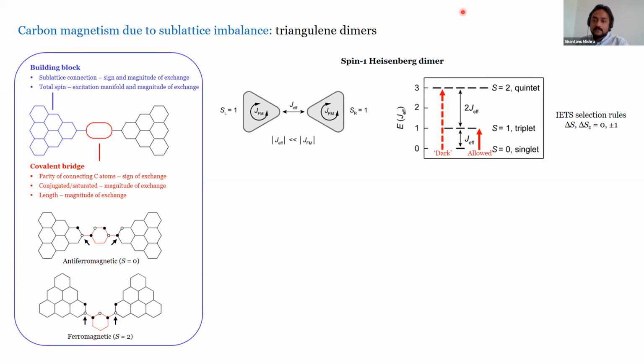And if we now go ahead and actually connect these two triangulenes together, they actually fall pretty close to a spin 1 Heisenberg dimer, in the sense that the intra-triangulene ferromagnetic coupling, which is this J ferromagnetic, is actually huge. And when we connect them together, the effective exchange coupling between these two units is going to be much, much smaller than this intra-triangulene ferromagnetic coupling.